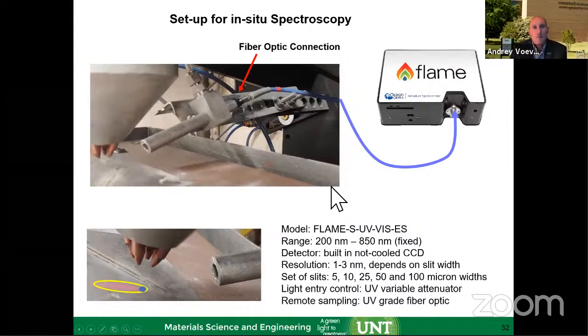So for the light collection from that melt pool location here, we're using the collimating tube, which is essentially a pipe of known diameter. We have a lens in here, and this way we protect the lens from the powder being deposited on it and changing the intensity of the signal. And then that lens is focusing it on a fiber optic, and the fiber optic is then taking that signal out to the spectrometer. We're using the Ocean Flame spectrometers in here.